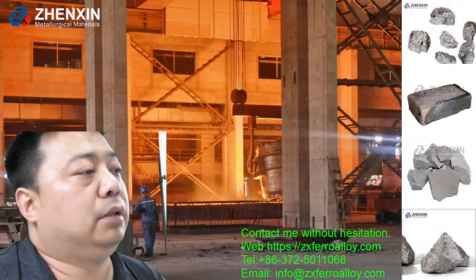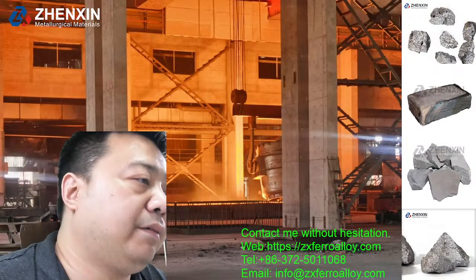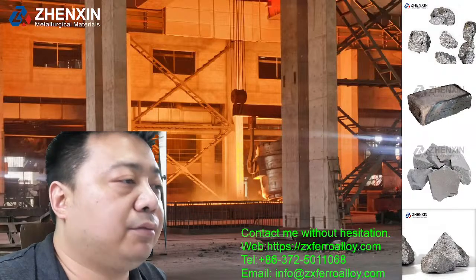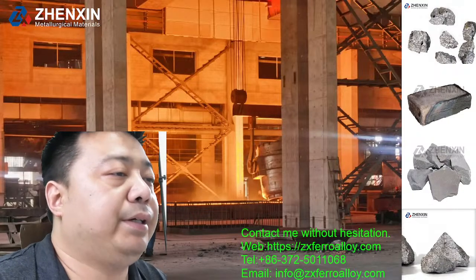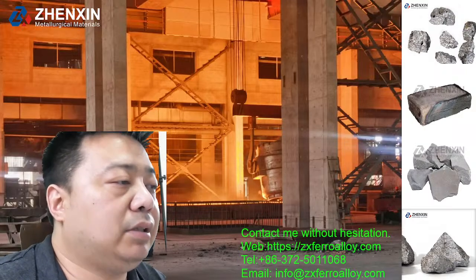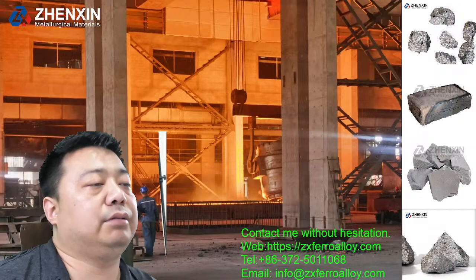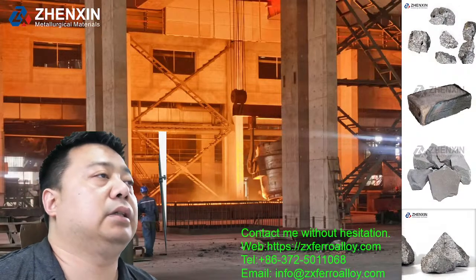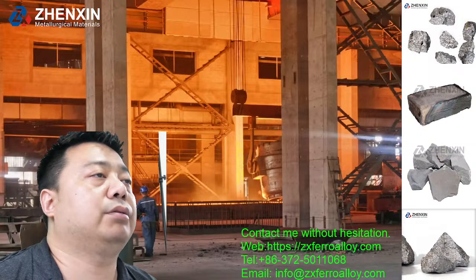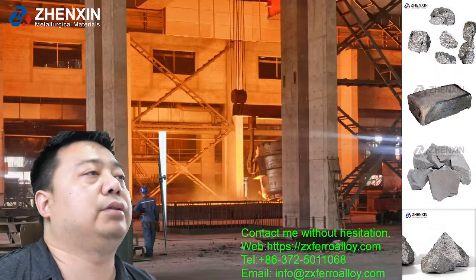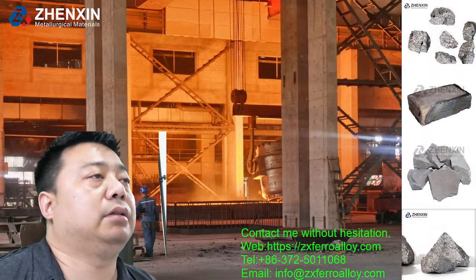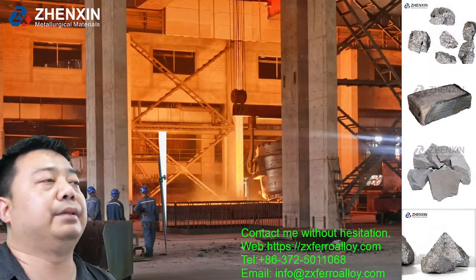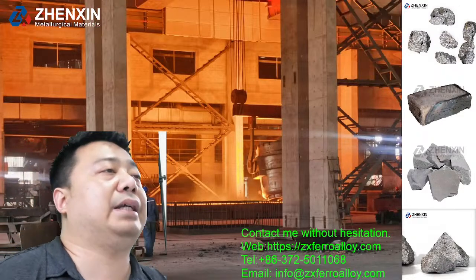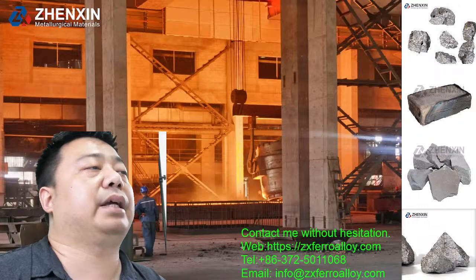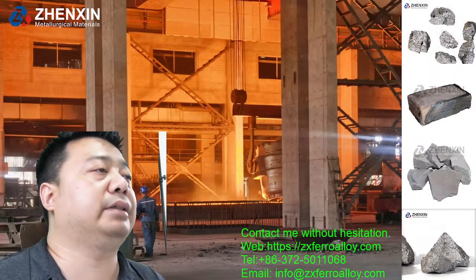Use a mixture of 28 to 35% calcium particles and 65 to 72% iron powder as the core layer of the calcium alloy wire, and the outer layer is wrapped with a cold rolled low carbon steel strip to make the calcium alloy wire. This kind of operation mainly uses iron to increase the specific gravity and the melting temperature of calcium particles, so as to reduce the rate of calcium evaporation and reduce costs at the same time. In addition, the iron powder itself has a certain weight, which can speed up the sinking speed of the calcium cored wire so as to quickly reach the ideal position.